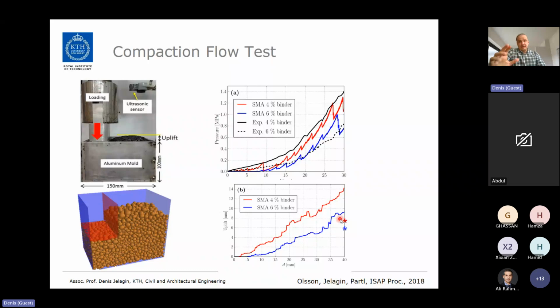And there we have access to the full history of uplift. And here we have 2 points coming from experiments. In experiments, we measured uplift only at the end of the test. And again, agreement is at least qualitatively in the ballpark of what we predict. This is actually as good as it gets with such an unrepeatable material as uncompacted asphalt mixture.